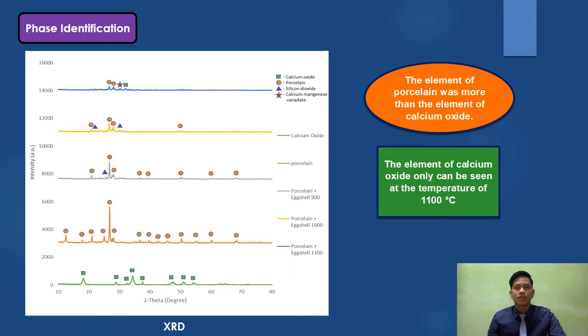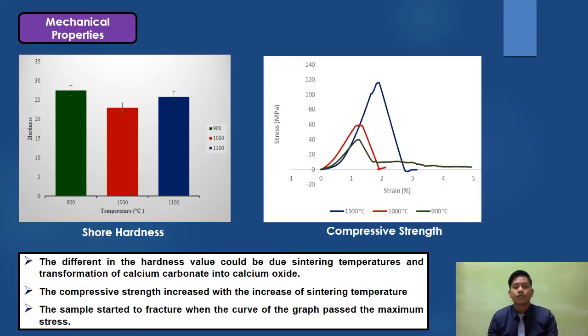This is because the mixing ratio of the porcelain was higher than calcium oxide, which is 80% porcelain and 20% eggshell. The element of calcium oxide can only be seen at the temperature of 1100 degrees Celsius. The presence of moisture in the air facilitated the hydration of calcium oxide to calcium hydroxide, resulting in portlandite in calcined eggshell powder. Let's move on to the mechanical properties results.